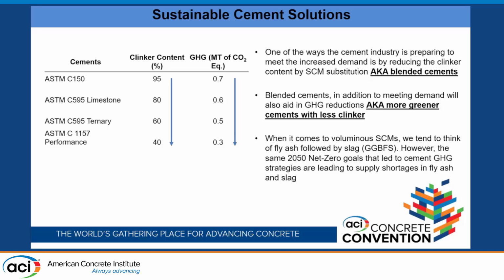So back in the day, we had ASTM C150 cements, which had up to 95% clinker. That was close to a ton of CO2. Now we are using limestone cements. They have clinker up to 85%. That reduces the GHG. The end goal is to produce ternary cements and performance-based cements, which will have a clinker content around 40 to 50%. That's almost like a 50% reduction in GHG just by dropping the clinker content.